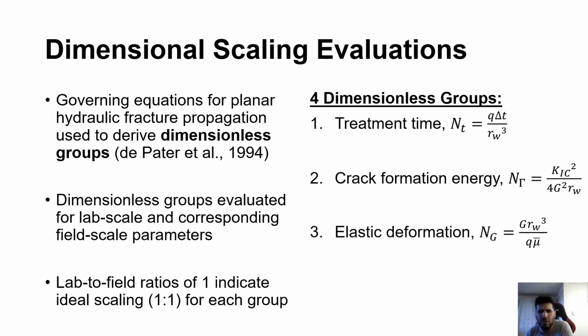The third dimensionless group is the elastic deformation, N sub g, equals G R_W to the power of 3 divided by Q times the effective viscosity of the fracturing fluid, mu bar, and that is for a flow into a planar fracture. And finally, the confining stress dimensionless group, N sigma sub C, which is equal to the confining stress sigma sub C divided by the fracture modulus G.